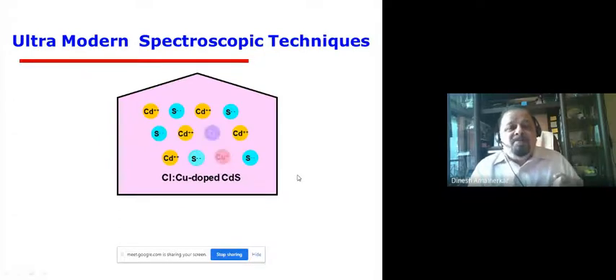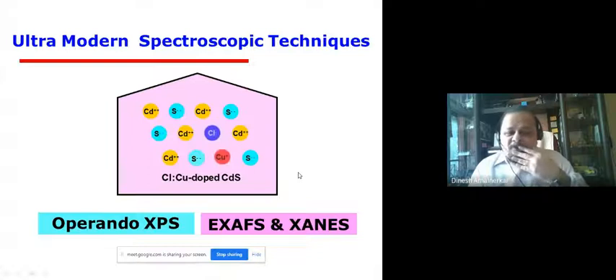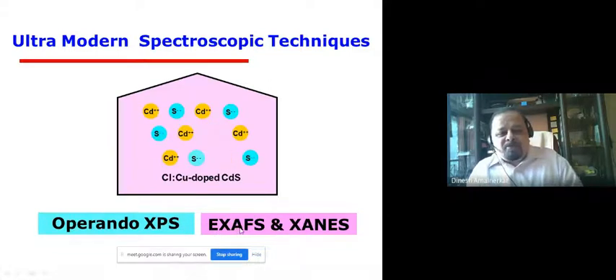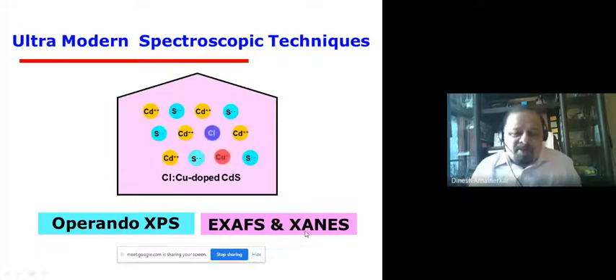And then later on, we confirmed by important techniques called Operando XPS. This is X-ray photoelectron spectroscopy, and these are the two other techniques: extended X-ray absorption fine structure spectroscopy, EXAFS, and XANES, that is X-ray absorption near-edge structure spectroscopy. We could get good results with these two techniques, which we cannot do anywhere in India, for which we caught hold of our Slovenian collaborator, who has access to the synchrotron radiation facility available in Trieste in Italy. They have regular beamtime there, and they did some analysis for that.